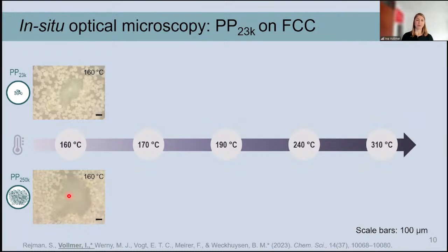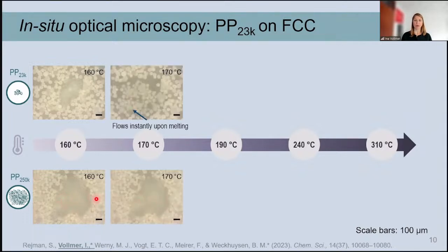and the catalyst. So we took a video of this process of converting polymer over a catalyst, and you see here these white dots, which are the catalyst particles, and then on top you see this blob of polymer. And right now we are still below the melting point of these polymers, and the difference between the top and the bottom is that the top is a low molecular weight polymer, so a short chain, and the bottom is a high molecular weight polymer, which is a very long chain. And so if we then go to the melting point of the polymer, you see at the top that these shorter chains are really melting and flowing into the catalyst bed. So here you have good contact between the polymer and the catalyst particles.